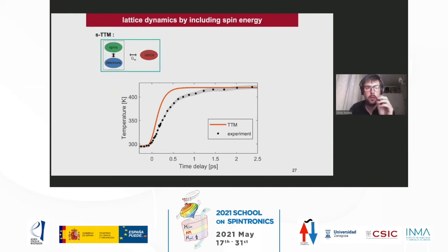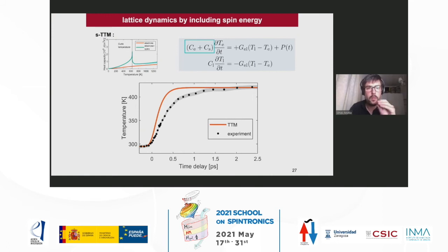We added to the electrons the heat capacity of the spins. So it's still a simple two-temperature model, but in this case we added the specific heat of the spins to the electrons. If you remember, electrons plus spin diverge or increase around the Curie temperature, and since the electron system goes above the Curie temperature, the sum of electrons and spin is larger than the electrons alone, and increases a lot.